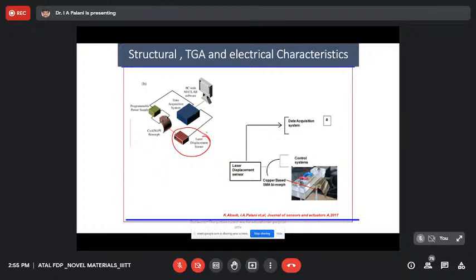What we are trying to do is connect this copper-based shape memory alloy to the programmable power supply, and there is a laser displacement sensor. The main application of this laser displacement sensor is that it has a source and a detector. The light falls from the source and gets reflected back to the detector. We have a copper-based SMA bimorph, which has a reflecting surface. So when there is an actuation, the laser will move back and forth through this reflecting surface, and from this we can estimate the life cycle which is happening. It is something like this.